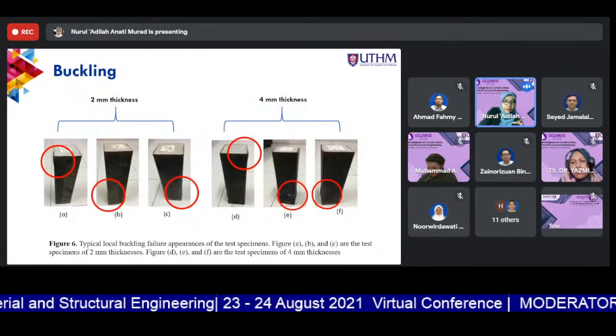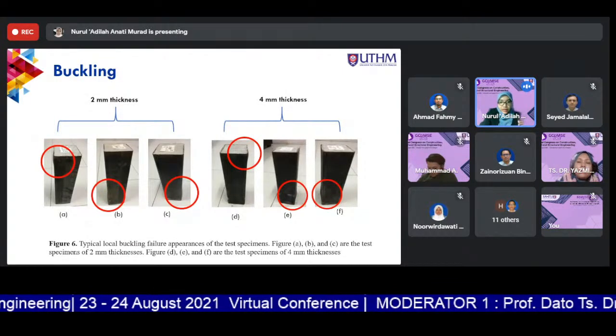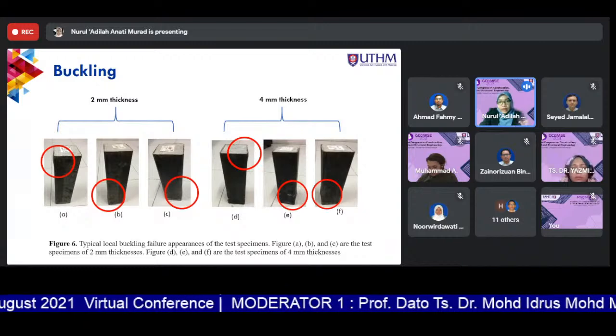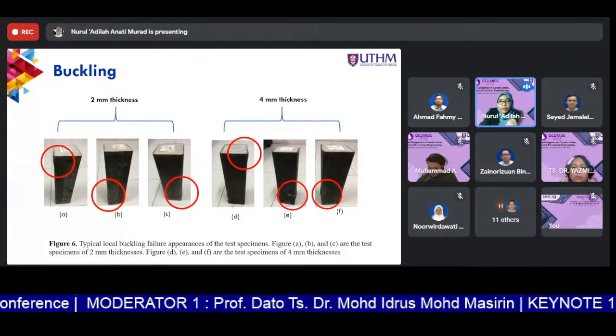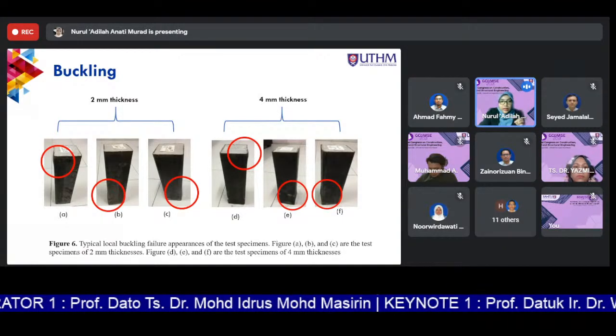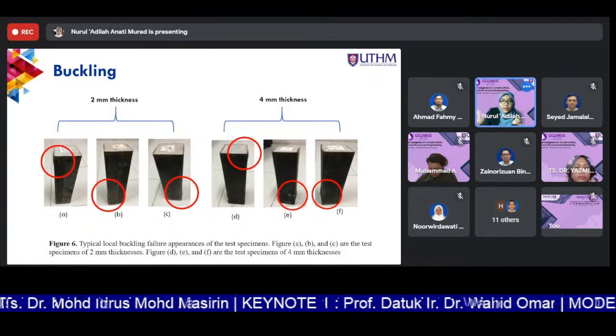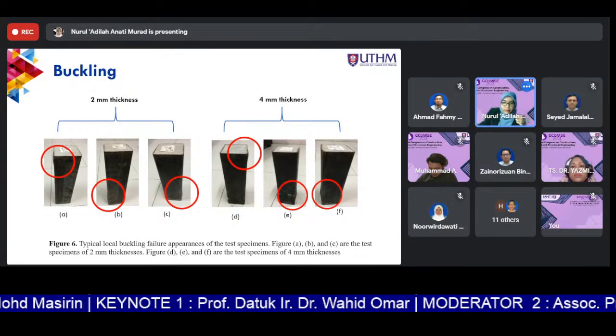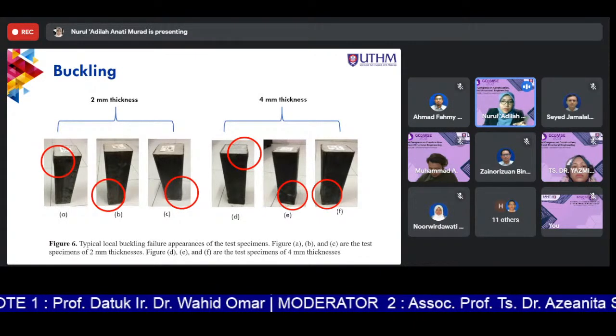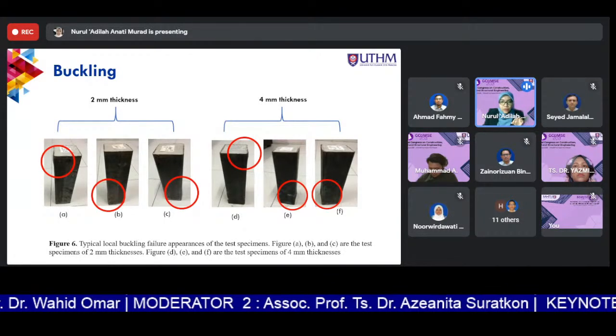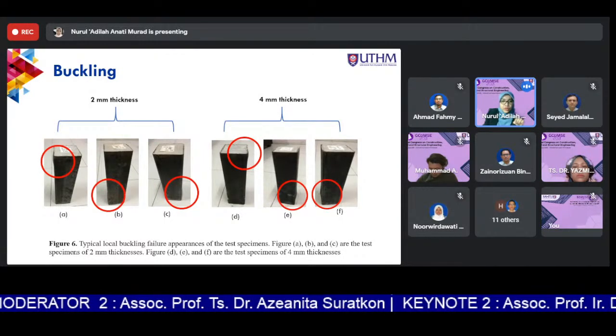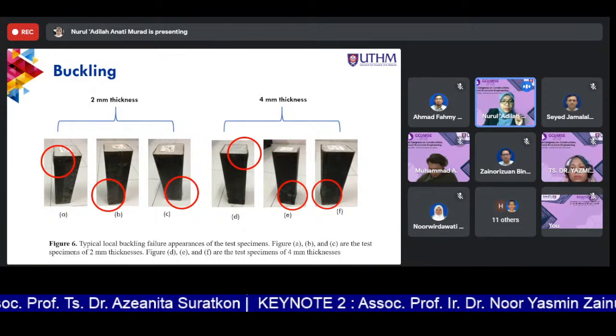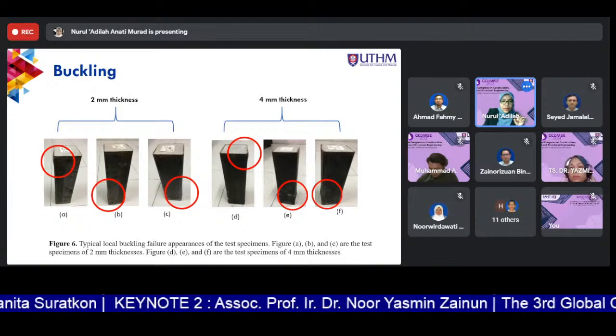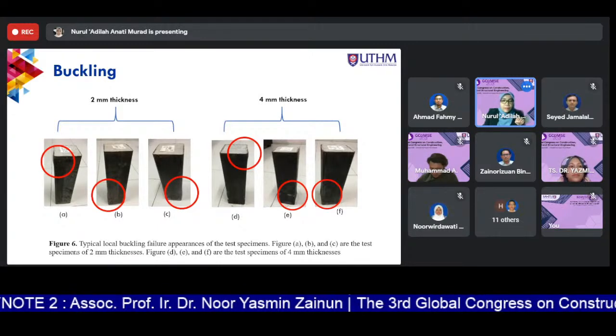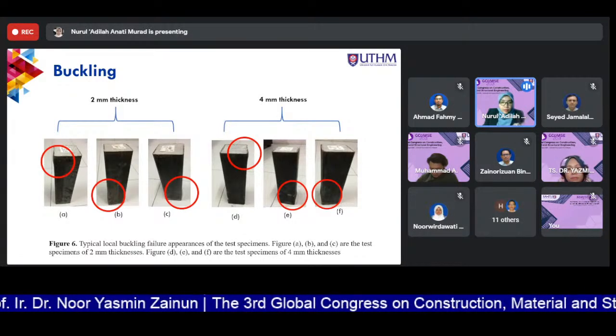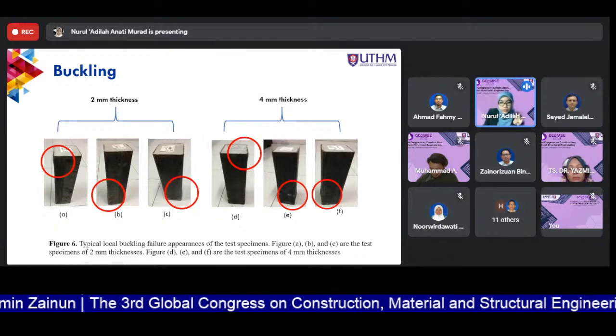Okay, and here is the specimen that shows the typical local buckling failure appearance of the test specimen. On the left is the 2 millimeter thickness and on the right is the 4 millimeter thickness. And both thicknesses show local buckling at top and bottom. And it is a common local buckling that occurs. And this is the specimen for the concrete hollow section with fly ash for 2 millimeter thickness. Sample 2 shows the bottom local buckling happening, while sample 3 shows no local buckling at all. And for the 4 millimeter thickness, both show top and bottom local buckling.